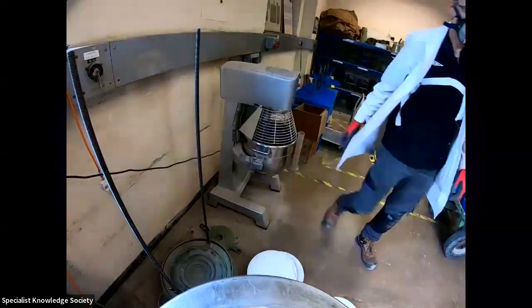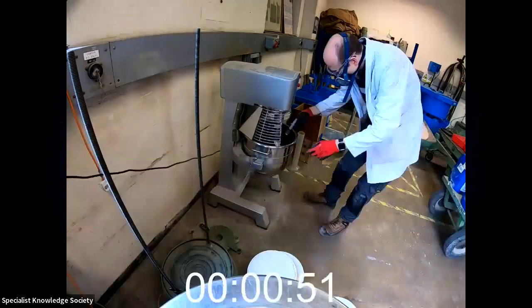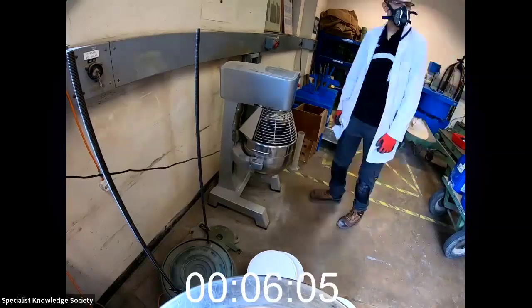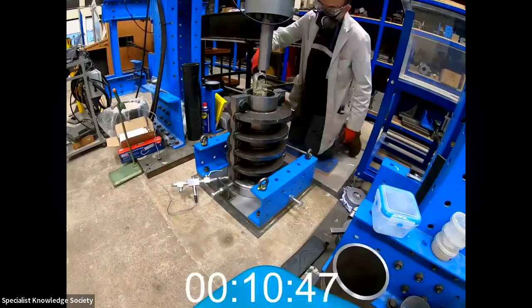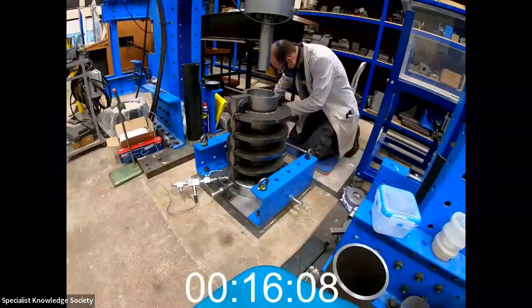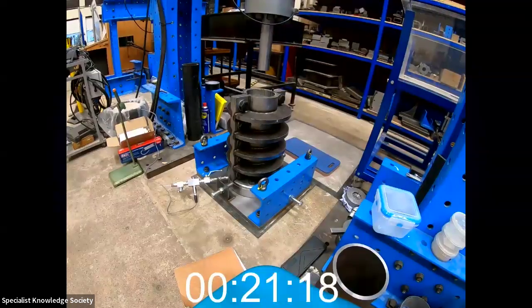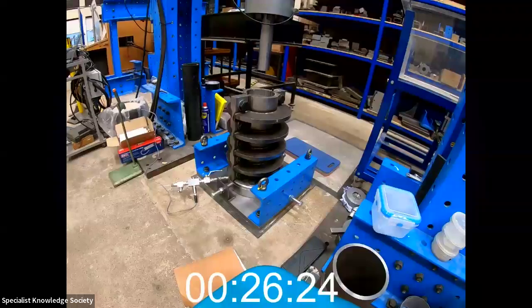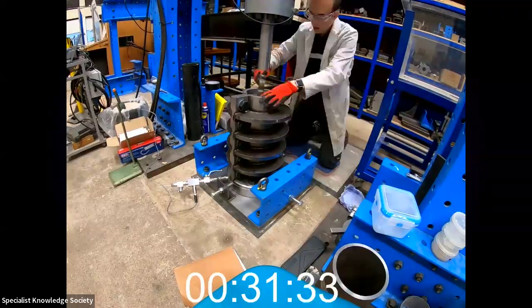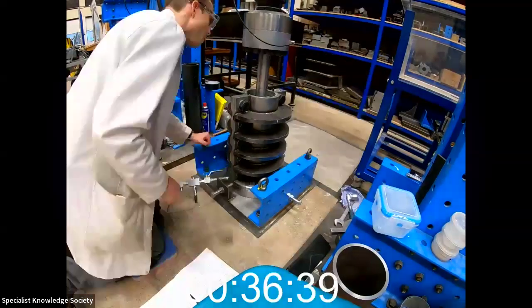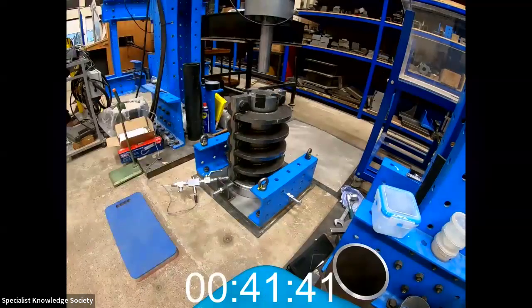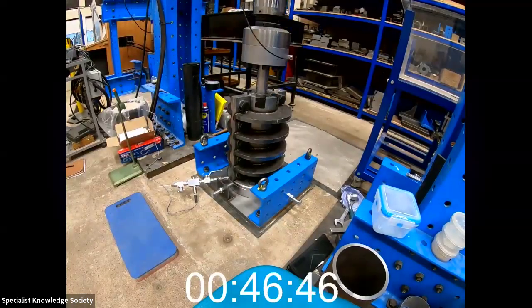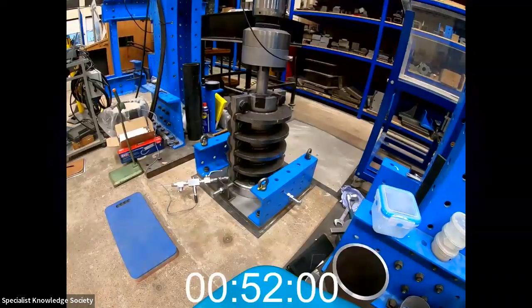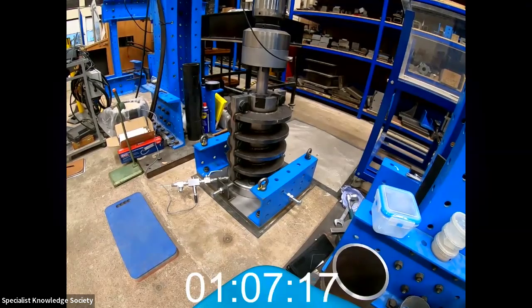So this isn't me just having had too many cups of coffee. This is a sped up video of the whole test process. So this is from mixing the materials right through to forming the sample. So we've put a lot of instrumentation on this rig, so we're controlling the deflection rate to simulate the injection process with the servohydraulic actuator, measuring the stresses in the sample, recording these with the data logging system, looking at even things like pore pressure within the sample.